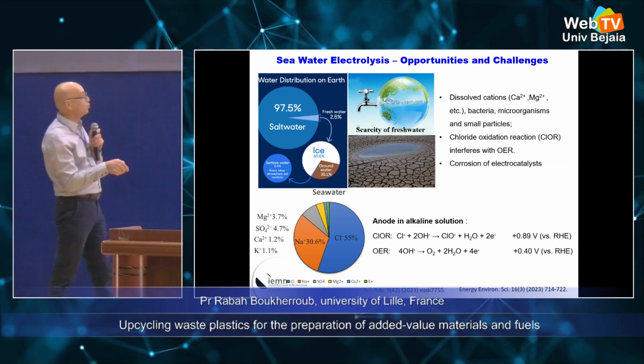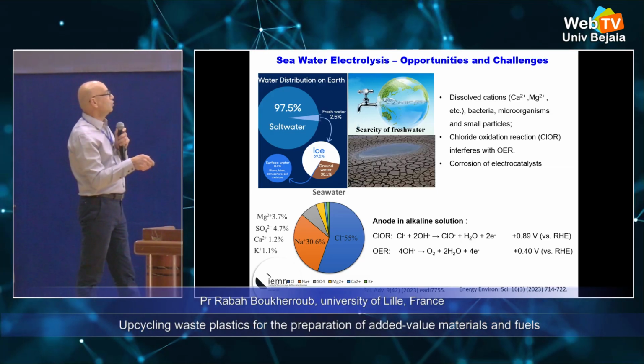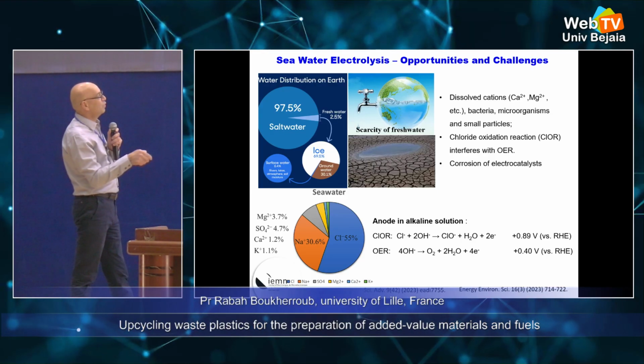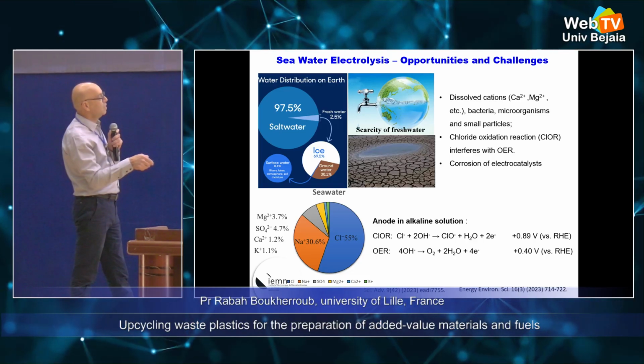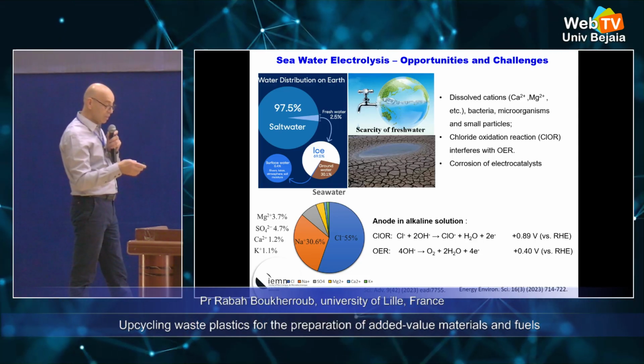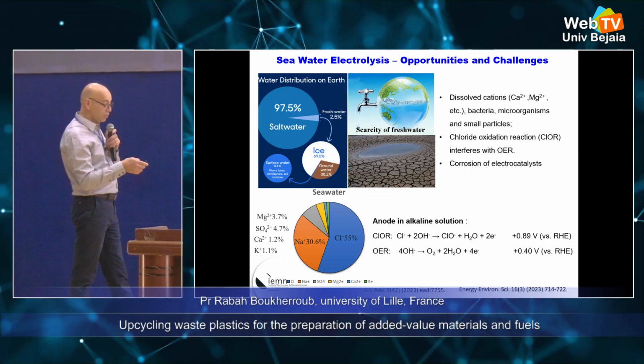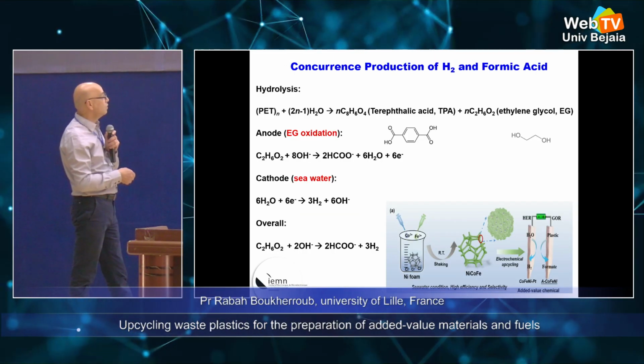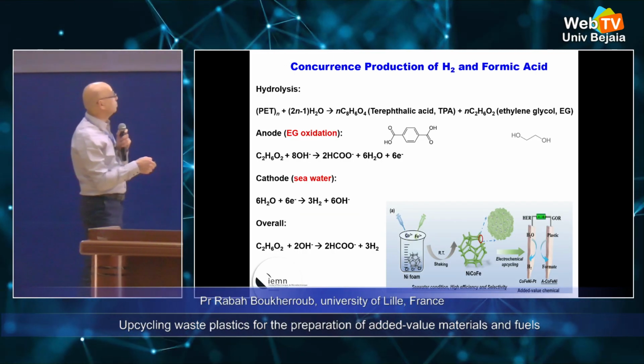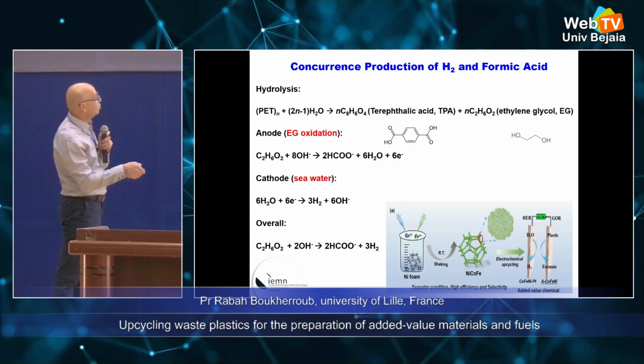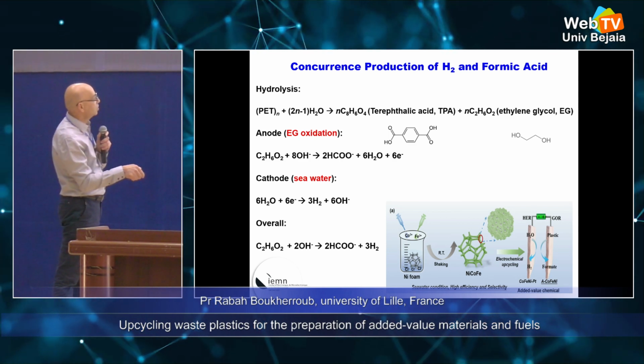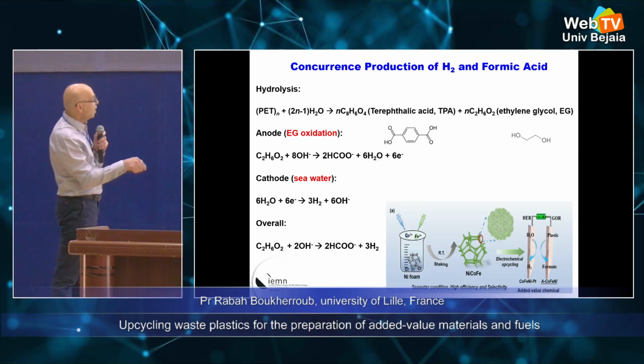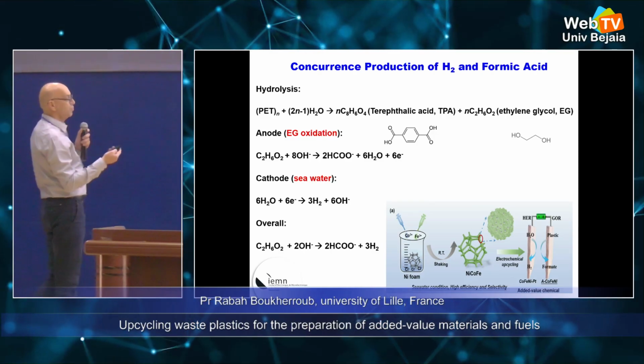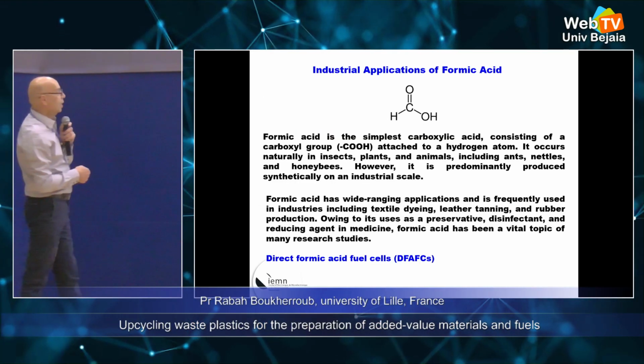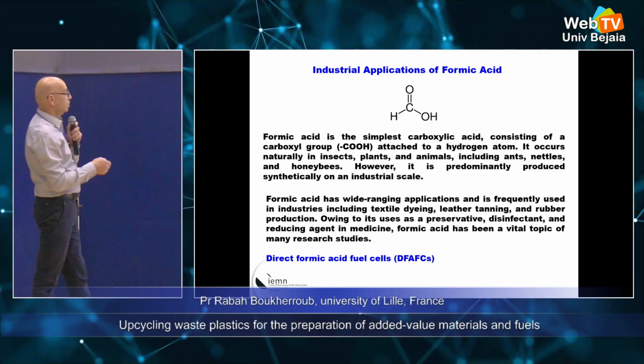Like anything in sodium chloride is not stable. And on top of that, you have a lot of dissolved cations or bacteria, microorganisms that can potentially absorb on your electrode surface and contaminate it. So what we did here, we hydrolyzed the PET, and we took the ethylene glycol and oxidized it to formic acid, and on the cathode, we generate hydrogen from just the seawater, a reduction, okay?